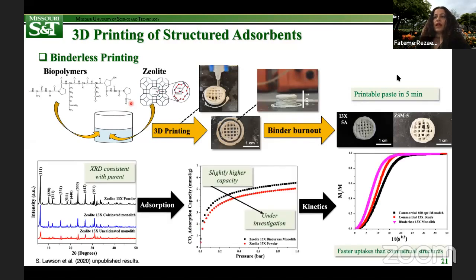All right, the XRD patterns here that you see confirm consistent crystallinity with the parent zeolites. To demonstrate this proof-of-concept investigation, we utilized these binderless zeolite monoliths in CO2 capture and observed faster uptake than commercially available beads or monoliths. Also, I should mention that, as you can see from here, the structured adsorbent exhibited slightly higher equilibrium capacity than the powders, which is currently under investigation as to how or why this is happening. But we repeated these synthesis procedures and made different batches, and every batch gave the same behavior.